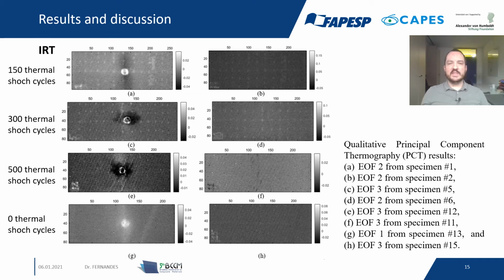Here in our work, we inspect the specimens with infrared thermography in the pulse thermography reflection mode setup, and then we applied PCT in order to improve the quality and the visualization of the results. Here we show the second and third components from all the specimens. We are showing here the best component, which brings more details. Here in the first row we have the 150 thermal cycles, second the 300, the 500 and the 0.